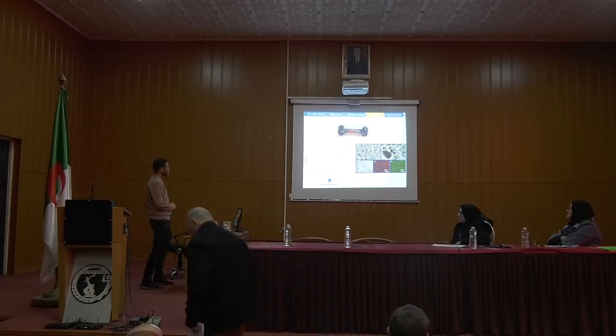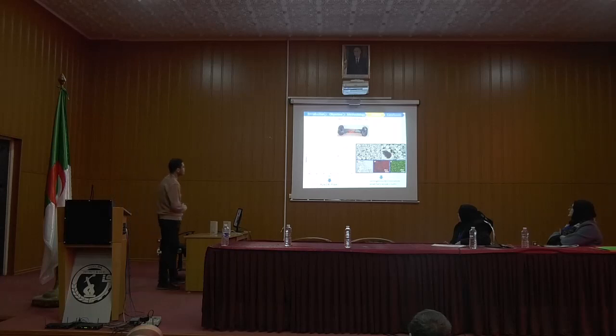We can say that the X-ray analysis shows a phase pure zirconium diboride. And also for the AFM analysis, we can see here that we have a homogeneous microstructure. Also, the EDX results show that the microstructure was homogeneous all around the sample. And also the particle size, which is a very important factor: here we have a small particle size, less than a micron.